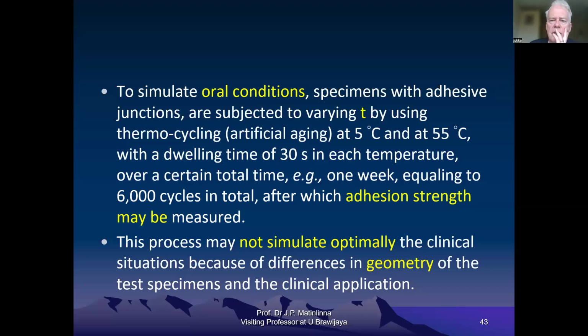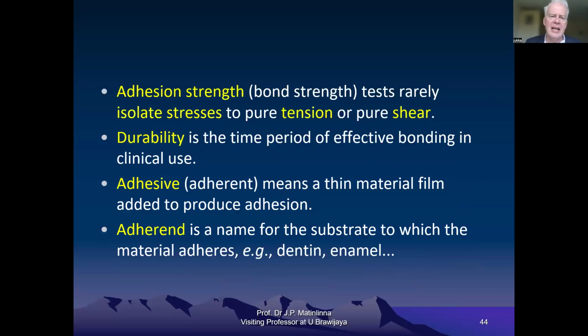To simulate oral conditions, specimens with adhesive junctions may be subjected to varying temperature by using thermocycling, artificial aging between +5 and +55, with a certain dwelling time in each of the temperatures over a certain total time equaling thousands of cycles, after which we measure the adhesion strength. This is a laboratory process. It doesn't simulate optimally the clinical situations because of the differences in geometry of the test specimens and clinical application. Adhesion strength tests rarely isolate stresses to pure tension or shear.